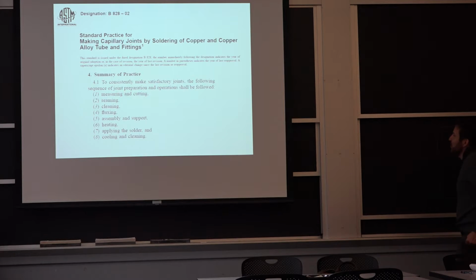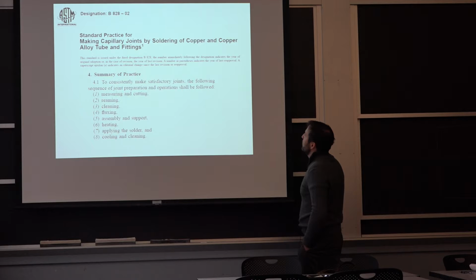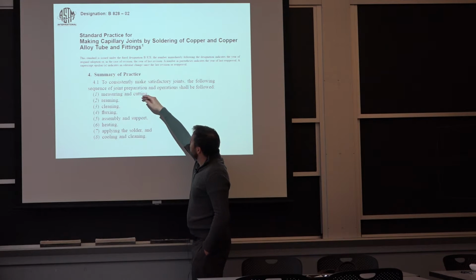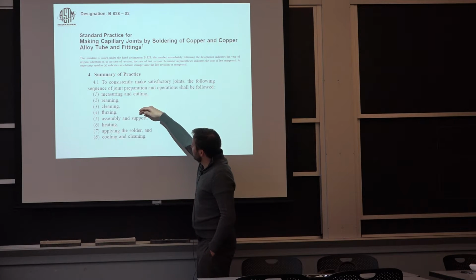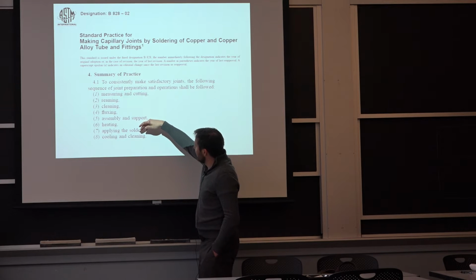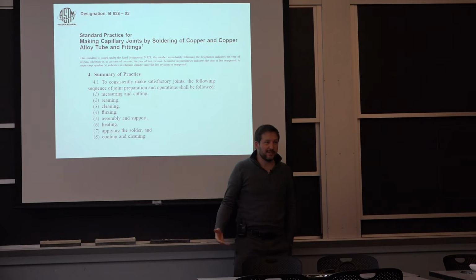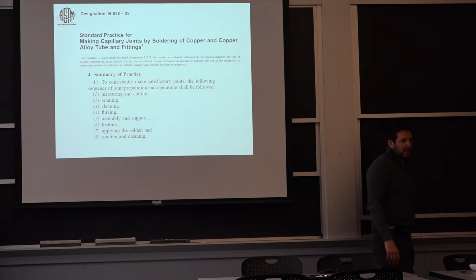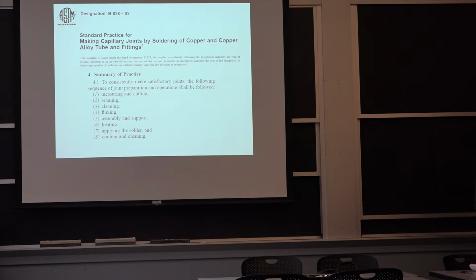So it's an unfortunate example. Standard practice for making a joint: you measure, you ream, you clean, you flux, you assemble, you heat, you apply, you cool, and you clean. That's it. So it's one example where, say, the Copper Development Association arrived at a criterion. They said you want at least 70% of the joint filled. It's not unreasonable, you know, it's kind of a passing grade.